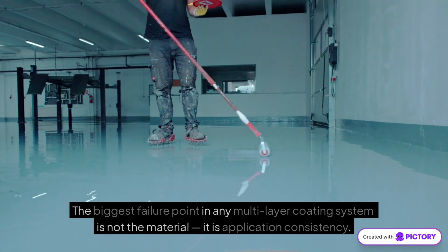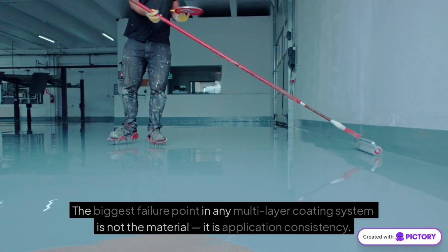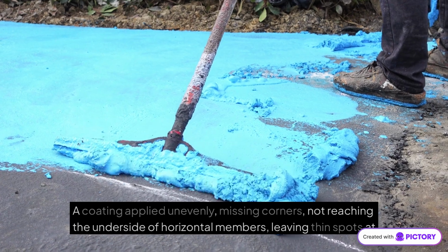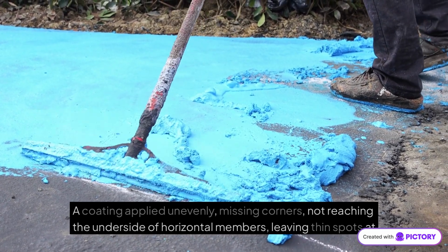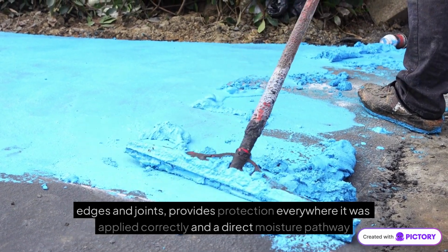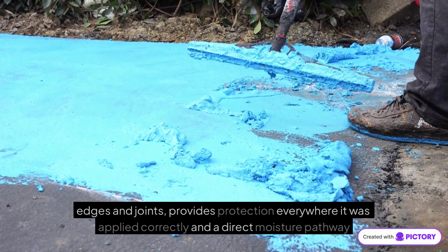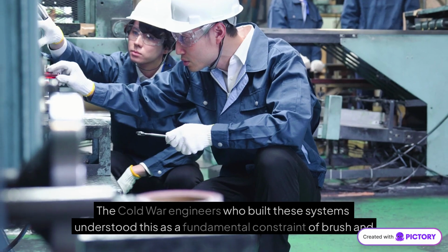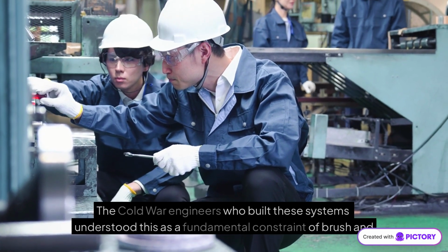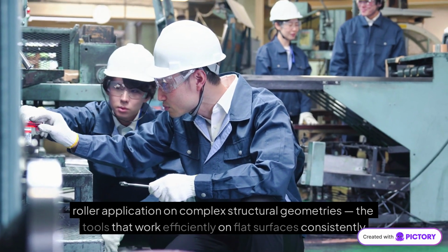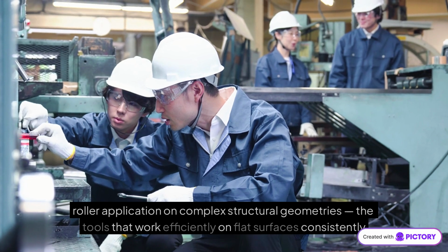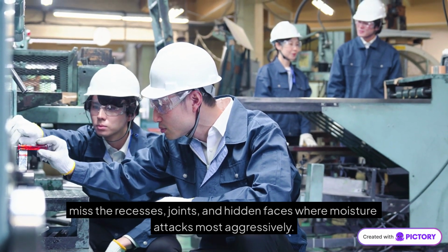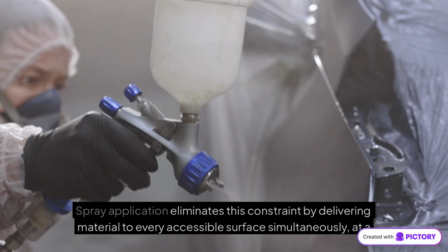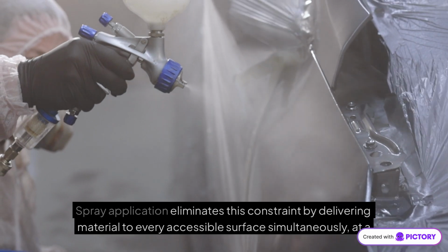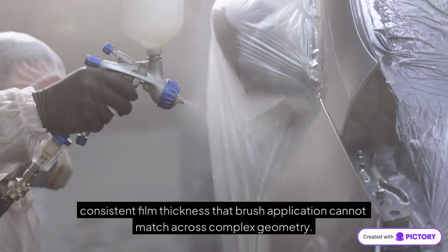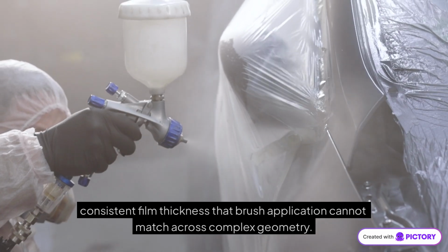The biggest failure point in any multi-layer coating system is not the material, it is application consistency. A coating applied unevenly, missing corners, not reaching the underside of horizontal members, leaving thin spots at edges and joints, provides protection everywhere it was applied correctly and a direct moisture pathway everywhere it was not. The Cold War engineers who built these systems understood this as a fundamental constraint of brush and roller application on complex structural geometries. The tools that work efficiently on flat surfaces consistently miss the recesses, joints, and hidden faces where moisture attacks most aggressively. Spray application eliminates this constraint by delivering material to every accessible surface simultaneously, at a consistent film thickness that brush application cannot match across complex geometry.